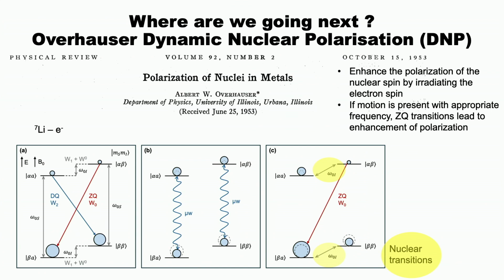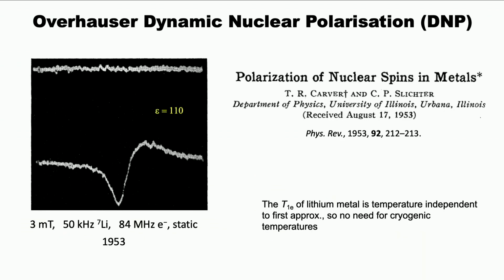He was in Illinois, and his colleague down the road replicated this experiment the same year. So this is an experiment by Tom Carver and Charlie Slichter, and what he did was he had little bits of lithium metal in a dilute matrix, and he got this massive enhancement of 110. And the signal, so he's down at 3 millitesla, so very low frequencies, and he didn't even get the signal of lithium metal without irradiating. He worked it out based on comparing with some proton experiments. So these were experiments of 1953, and I thought, well, maybe we could do this in 2023, or 2020 more accurately.